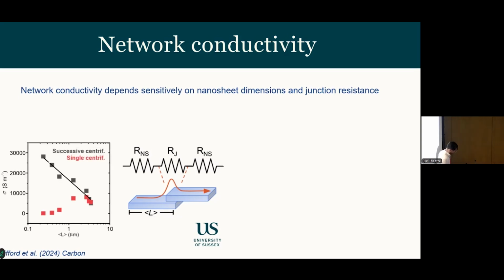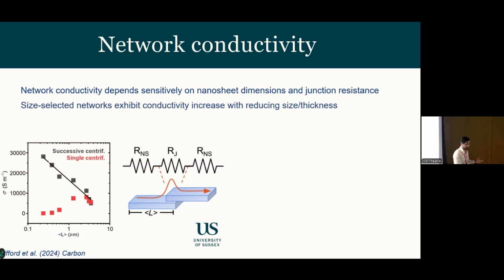So when we perform these measurements, there are two data sets here. One of them, in red, is what I've called single centrifugation. When we just skim the big stuff out and keep the successively smaller stuff, of course, we also retain all of the excess surfactant, and we see the conductivity drop off in the red. However, when we use this liquid cascade centrifugation technique, we're effectively washing, as a standard washing process people would use for the likes of sol-gel synthesis and this sort of thing. We remove all the excess, and we actually then start to see this emergent behavior where the conductivity continues to increase as we make the sheet smaller. This is counterintuitive, because the trend in the field has typically been bigger sheets are better, larger junction area, lower junction resistance, and you start to see the inherent properties of the materials.